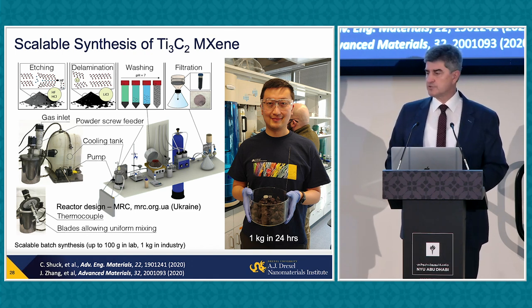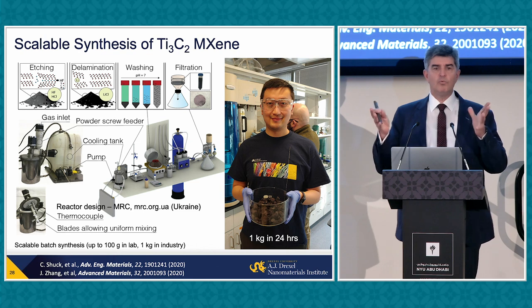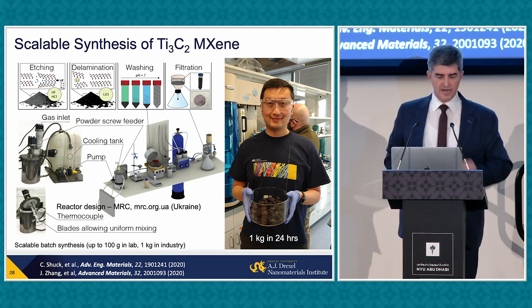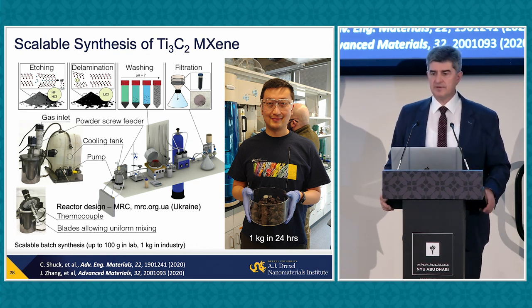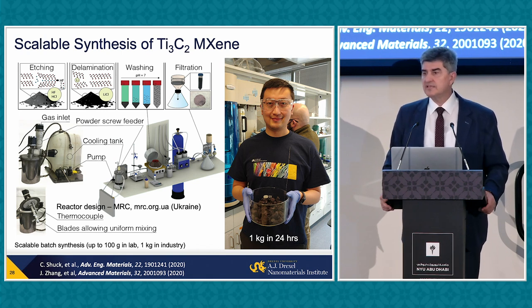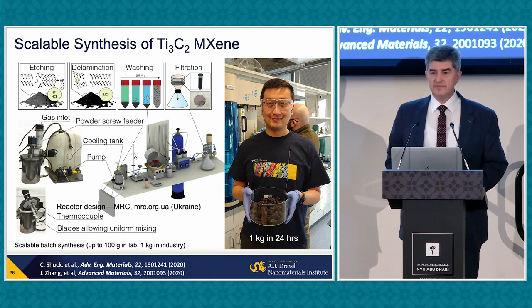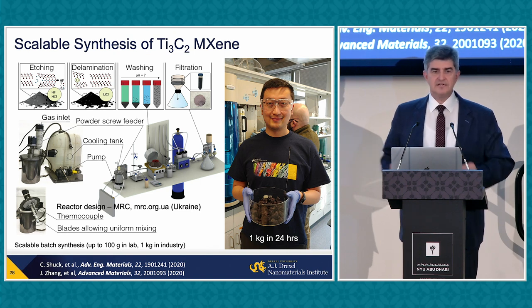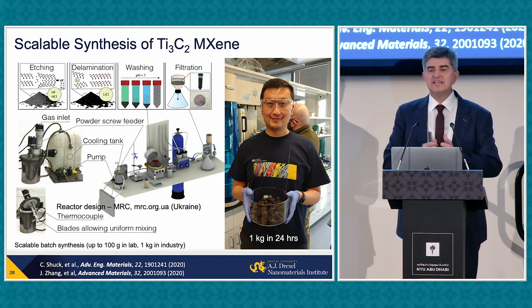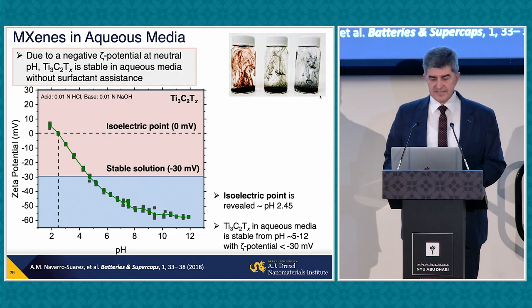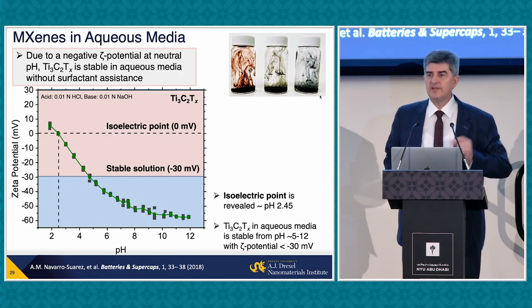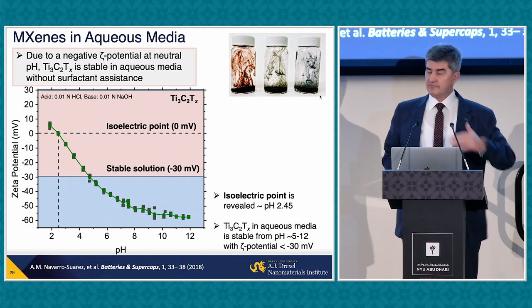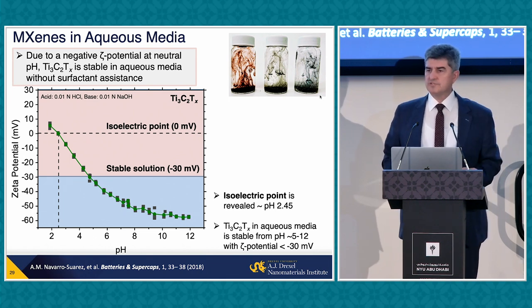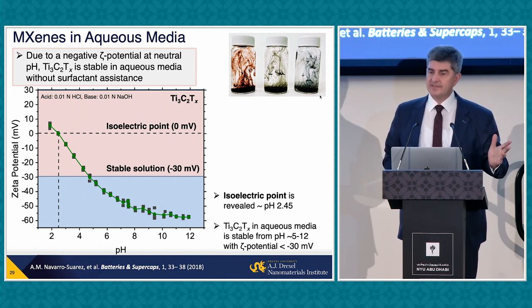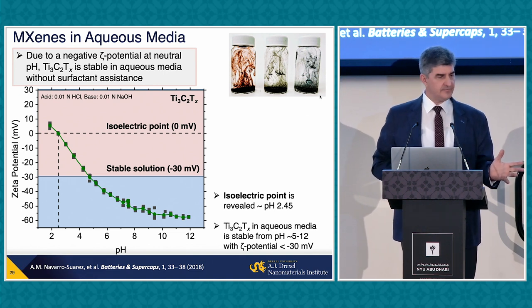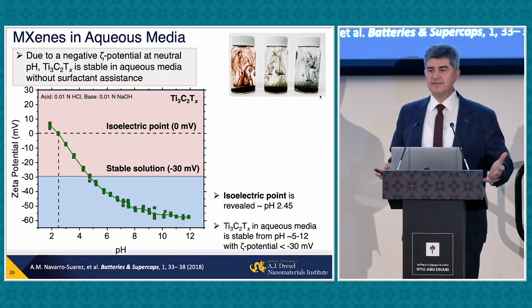This is one of my postdocs, John Zhang, holding 1 kilo of MXene produced using a reactor designed for us by the Materials Research Center in Ukraine. In 24 hours, we made this material. Another 4 days of the week, and we delaminated it all in solutions. Moreover, what is also wonderful about these materials, we have oxygen and OH on the surface. So they are hydrophilic like clay. Consider them to be a conducting clay or water-soluble metal.